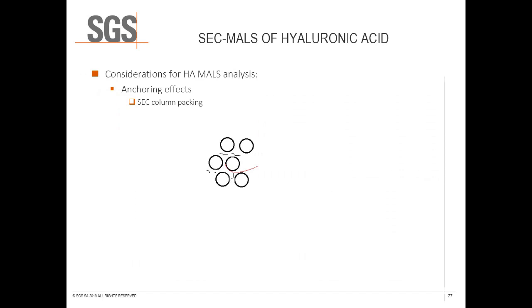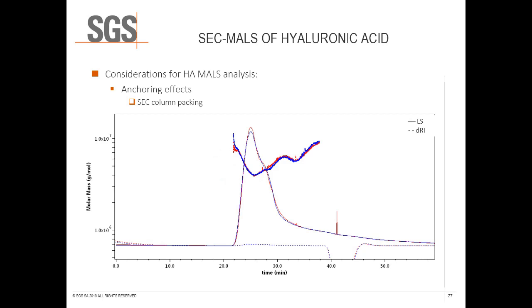Anchoring refers to polymer chains eluting later than expected due to their great size and their difficulty passing freely through the column packing, as shown by the theoretical red polymer molecule here. As polymer molecules pass through the beads of the column packing, very large chains tend to anchor. This may lead not only to extreme tailing and a lack of separation based solely on size, but also shear degradation for the polymer. This is exemplified in strongly tailing SEC peaks, such as the one shown. Molar mass plots may curve up significantly in the tail of the peak when anchoring occurs. Again, using columns with large particle diameters and pore sizes helps to reduce anchoring.